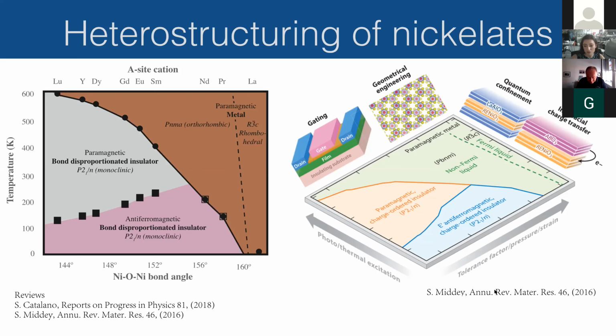So this is a picture I've taken from this review article where you have shown some examples of what can happen when you make a heterostructure. So of course you can start to build up devices. And when you have a material that has a sharp metal insulator transition, there are many reasons why you would like to make that into a device. You can play with different connectivity at the interface. There were some propositions a while ago that by growing in the 1-1-1 direction, you somehow get graphene-like structure. Quantum confinement, as I mentioned, if you make a film very, very thin, then you can have the orbitals that are in general symmetric or degenerate become non-degenerate just because it's out of plane confined.